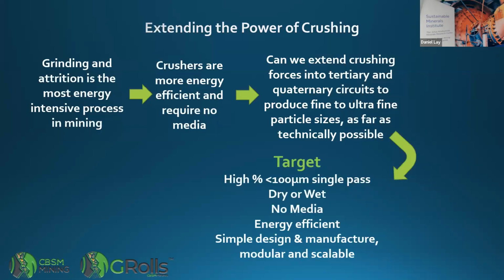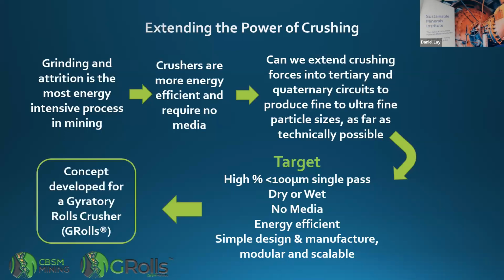So our target was to produce a technology that can produce a high percentage of less than 100 micron in a single pass. By doing that, you're reducing the recirculation loads. It can be used both dry or wet. Most comminution technologies are either dry or wet; they can't be both. Having no media is an important thing. Being energy efficient, and hopefully the use of the crushing forces helps that. A simple design, manufacturable, modular, and scalable, so we can get into those agile plants. So that's where we developed the concept for the Gyratory Rolls Crusher.